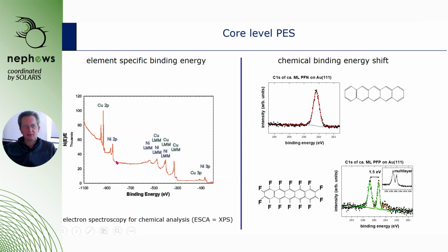We also get for free not only the core level photoemission from such a spectrum; since Auger processes also occur and Auger electrons are emitted, you also get the Auger transitions, which can further help you identify elements in your sample. For that reason, the historic name of X-ray photoelectron spectroscopy is actually electron spectroscopy for chemical analysis, or ESCA, which you will find in the literature as well.